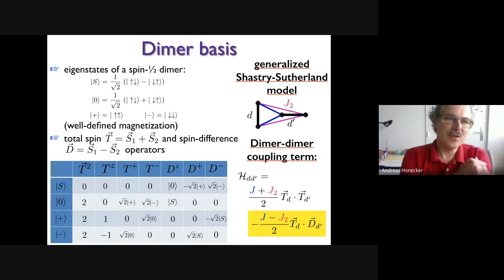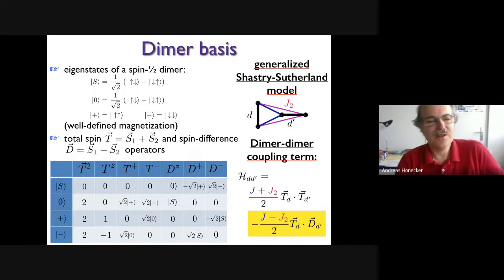For the Shastry-Sutherland model, the basis of choice is the dimer basis. So you pass to eigenstates of a spin 1/2 dimer, the singlet and the three triplet components. There's some freedom here, but we choose to work with a well-defined magnetization. In some sense, you can cast it in a different language by rewriting the Hamiltonian in terms of the total spin operator of a dimer and the spin difference operator of a dimer. If you then generalize the orthogonal dimer arrangement by introducing another coupling J2, you can write the dimer-dimer coupling sketched here in terms of the total spin times total spin coupling, and the correction term that couples the total to the difference.